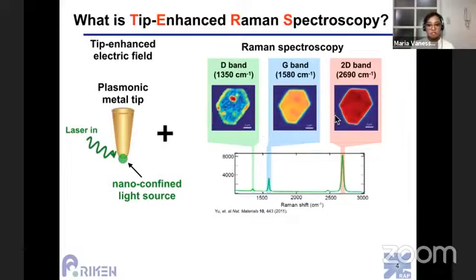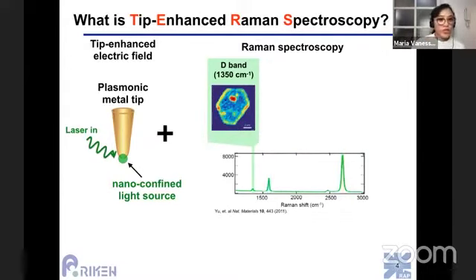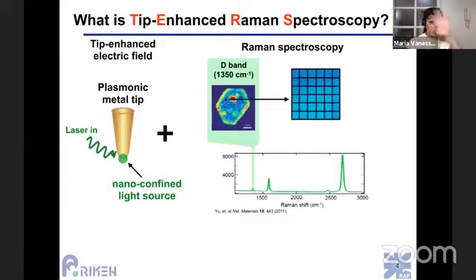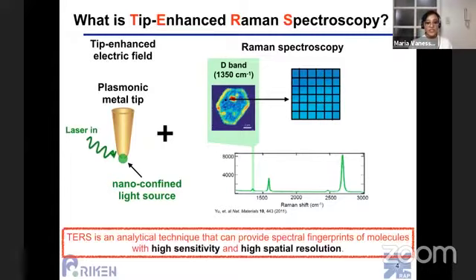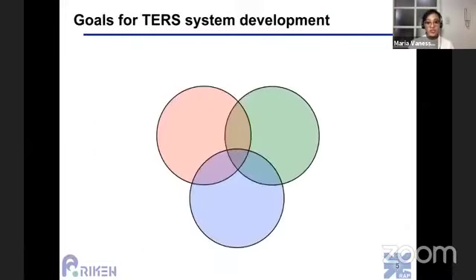kinds of information. Basically, Raman spectroscopy is done in the far field wherein you do a large scan of the sample. Here in this image, it's actually 10 microns by 10 microns. But for tip-enhanced Raman spectroscopy, we are actually interested only in 1 pixel of that entire image. And then in that 1 pixel, we want to image that small pixel to get the very local properties of our sample, which is why TERS has been dubbed an analytical technique with both high chemical sensitivity and also high spatial resolution.